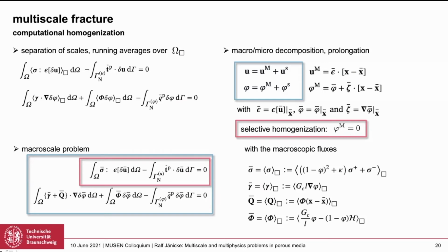Then we put everything into the weak form. We start our testing of macro and microscopic properties, and we end up with the macro scale problem here in the blue box, whose equation system has the structure of a phase field fracture model again. But what's quite fancy, if we assume the absence of macroscopic gradient, then we only end up with this weak format of the balance of momentum, where now the damage effect is hidden in how sigma bar is computed. And this is nothing else than a local damage model. So we have here a switch where we can say, okay, we would like to have a local or non-local macro scale damage model.